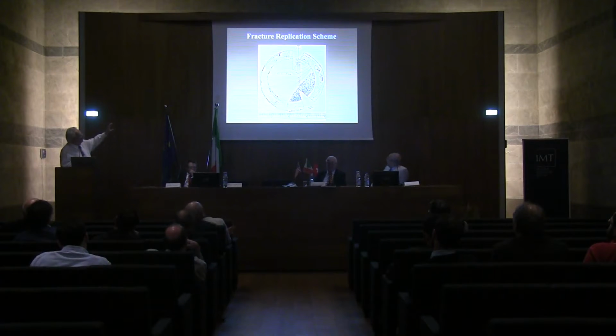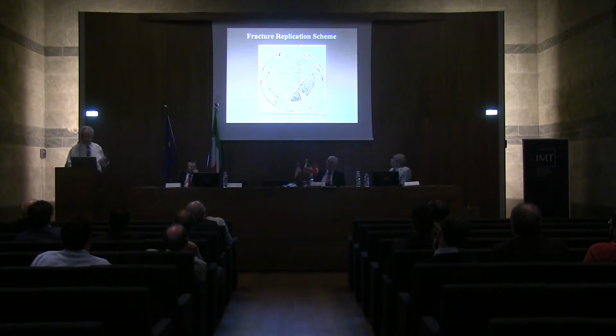So you can see that the beach mark, the fatigue portion, is much larger than the final rupture zone, which indicates the applied loads are relatively low. The bigger the portion that's by fatigue and the smaller the portion by final rupture, that means the applied loads are low. If we have a very small fatigue crack portion and a very large overload fracture zone, that means the stresses are quite high. And of course, we can't see the origin of the failure, but it appears there was only one origin location, although it's been cut out, which would indicate that stress concentrators are not a serious problem here.